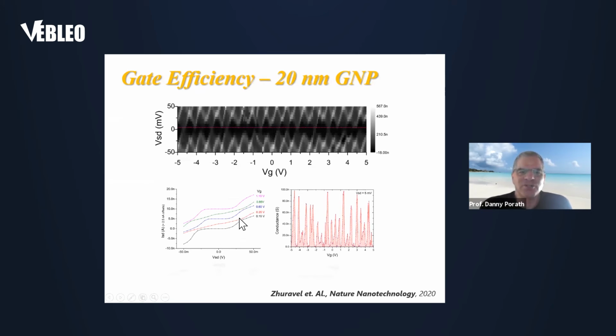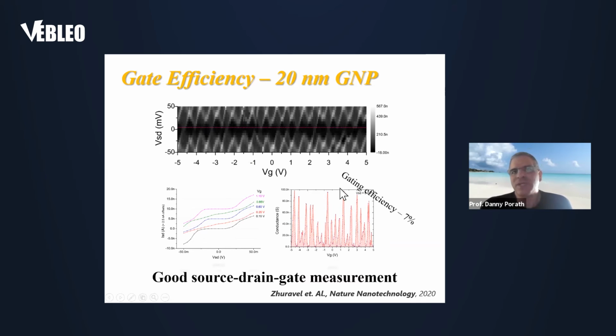In this case, we wanted to check the system. So we trapped a single 20 nanometer gold nanoparticle between the two electrodes, and we could see the stability diagram, the source drain voltage versus the gate voltage. And here you can see the derivative of the current, and these diamond-like structures tell us that indeed the Coulomb blockade is appearing and the junction works well. Another piece of information that we got is that the gate is sufficiently effective for the measurements.